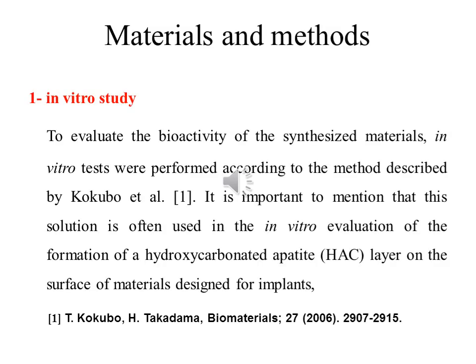For the in vitro study, to evaluate the bioactivity of the synthesized materials, in vitro tests were performed according to the method described by Kokubo et al. It is important to mention that this solution is often used in the in vitro evaluation of the formation of a hydroxycarbonated apatite HCA layer on the surface of materials designed for implants. We must mention the SBF is elaborated in our laboratory with the Kokubo process.